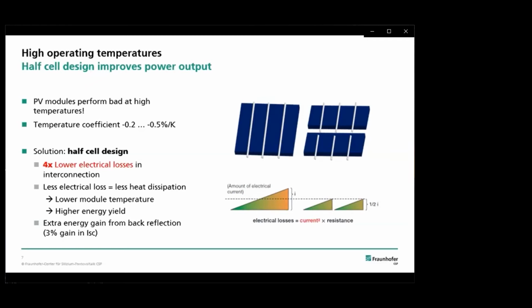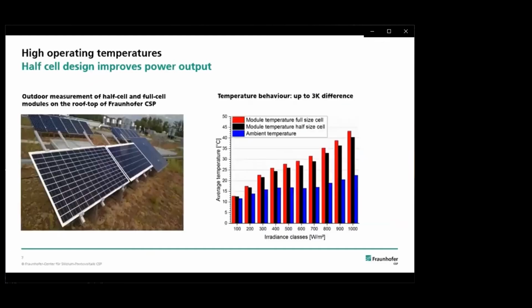And on the next slide, I want to show you some of the results which we had on half-cell modules. So here we fabricated the same materials, half-cell modules and full-cell modules, and put them on our rooftop at Fraunhofer CSP, and we looked at the temperature behavior, and we sorted, given in red, the full-size module, and given in black, the temperature of the half-cell modules. We had a temperature difference of more than 3 or up to 3 Kelvin, which is quite a lot and could give us like more than 1% of energy yield.